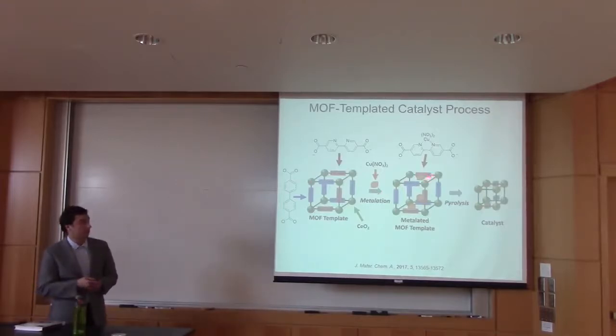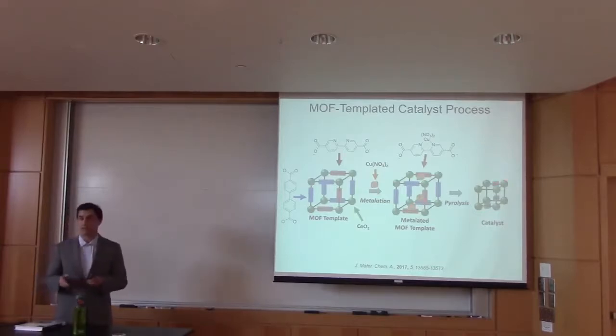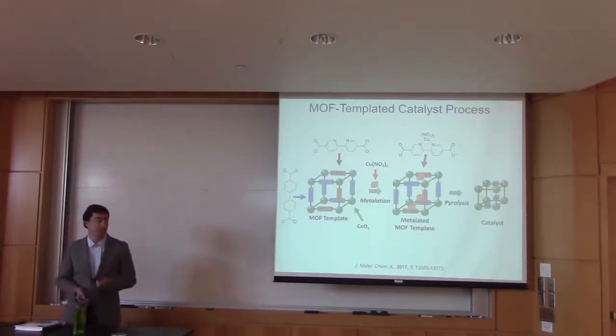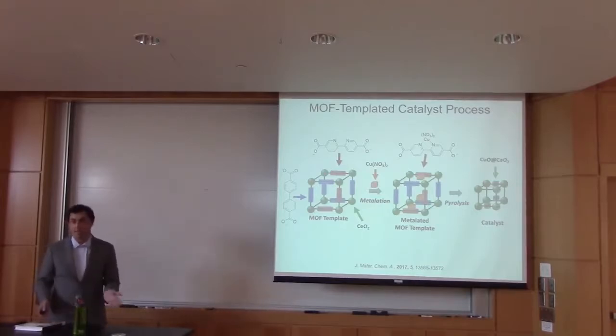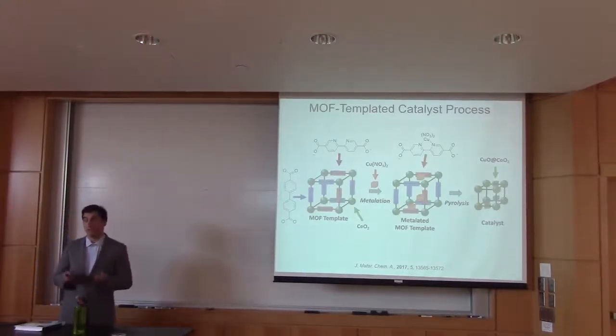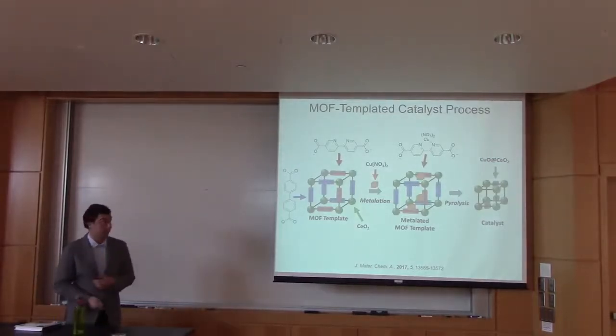So going from this orange cube, which is the copper salt, to these kind of grayish green cubes, which are copper oxides. And we're getting a copper oxide catalyst supported on ceria. What's nice about the tunability of these MOFs is we can control how much copper is incorporated into our MOF by controlling how much of this bipyridine ligand we use, and can hopefully evenly space out that copper in some ratio that we desire.